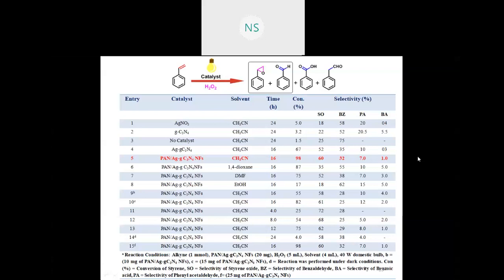So whatever catalyst we have used for this particular system, that catalyst is showing the highest yield of 98%, and when we go with the selectivity, styrene oxide is showing 60% or more. That is a major product formation taking place in parallel with the benzaldehyde as compared to benzoic acid and phenylacetaldehyde.